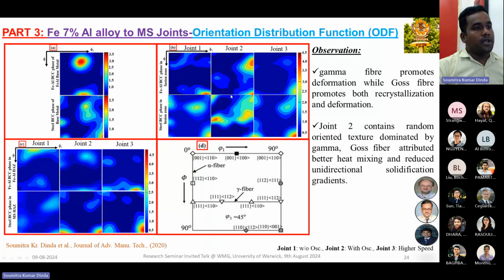So if we try to correlate this figure with the right-hand figures, both at the top and bottom, we can see that in case of joint 2, for both the Fe-Al alloy and the steel, we are getting gamma and Goss fiber compared to our joint 1 and joint 3. And this gamma and Goss fiber is attributed to better heat mixing and reduced unidirectional solidification gradient.